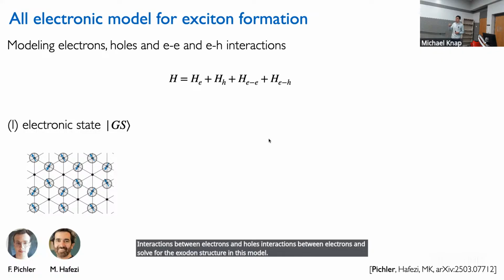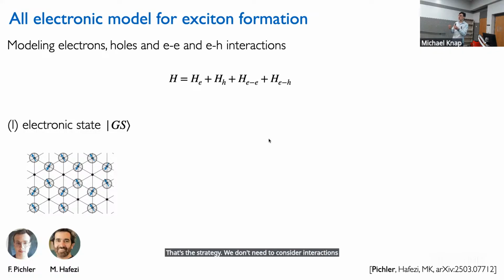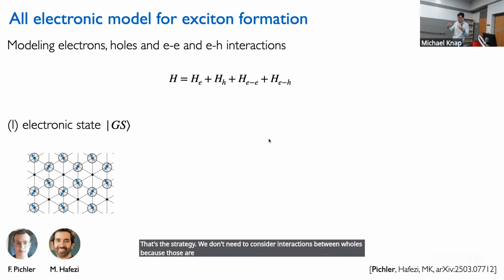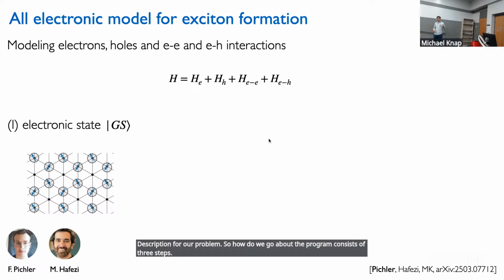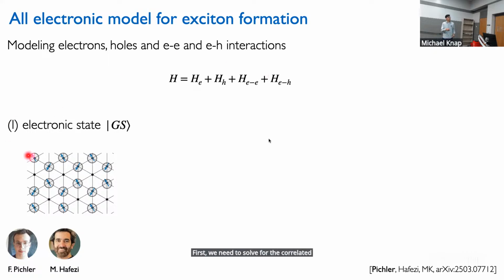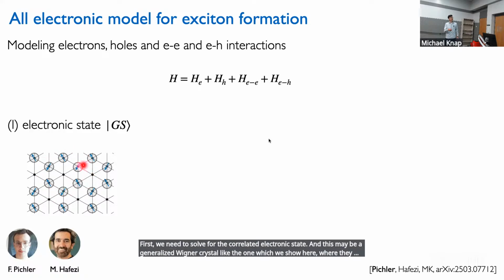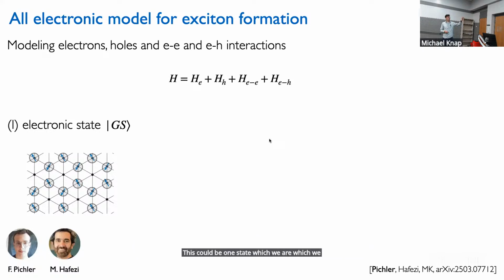That's the strategy. We don't need to consider interactions between holes, because we have the impurity limit of the hole, as we are thinking about a single impurity forming in the system. So the Hamiltonian is complete when we are considering a single band description for our problem. How do we go about it? The program consists of three steps. First, we need to solve for the correlated electronic state. This may be a generalized Wigner crystal like the one which we show here, where the charges are sitting on these hexagons, and in the middle, the sites are empty. This could be one state which we find by solving for the ground state of the system.